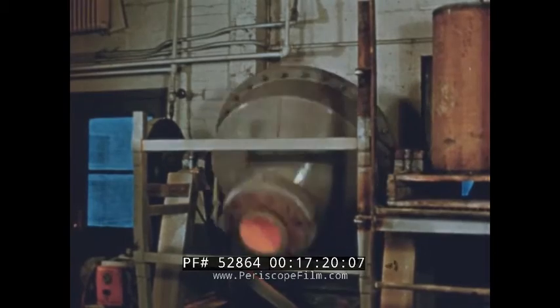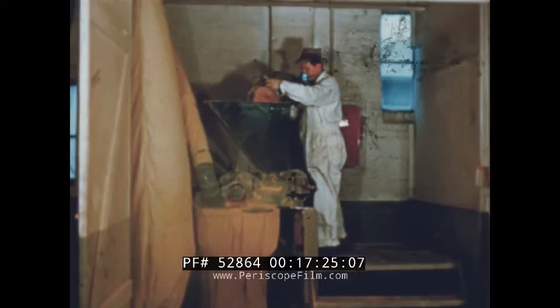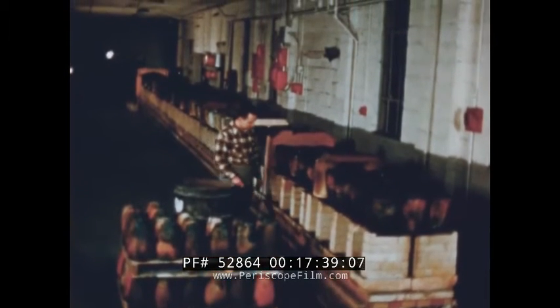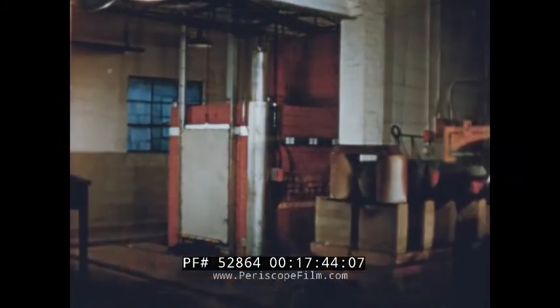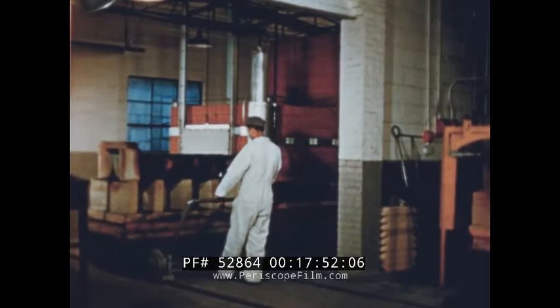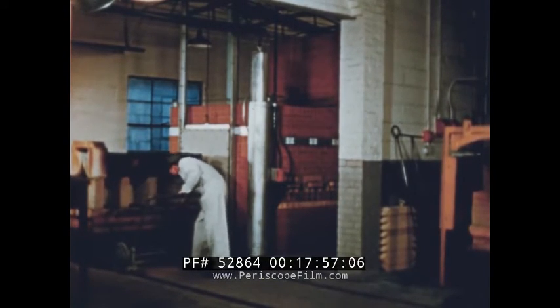Colors are needed for ceramic ware and porcelain enamel, and they must be inorganic in nature. Here in Pemco's oxide department, this yellow raw material is blended in a tumbler and ground in a micro-pulverizing machine. This particular color, after it has been calcined — a firing operation necessary for such colors — will appear pink. Following pulverizing, the stain is placed in crucibles on cars ready for calcining in a long Harrop kiln. Pemco began making oxides in the 1930s and was the pioneer frit manufacturer to do so. The oxide department manufactures 20 basic colors, from which no less than 30,000 shades can be obtained.